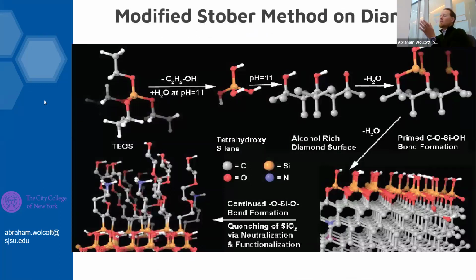So when we look at the surface of the diamond and we're doing silica chemistry, we start with this material, TEOS, or tetraethyl orthosilicate. It gets hydrolyzed to form tetrahydroxysilane. Then our alcohol groups on the surface of the diamond do a nucleophilic attack. You have a leaving group of water, and you form a silyl ether bond, a carbon-oxygen-silicon bond.